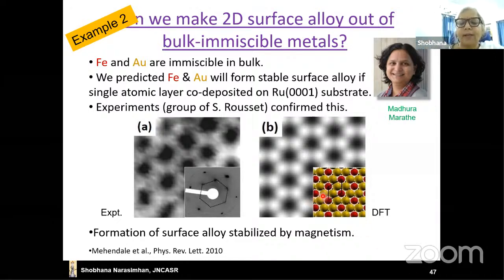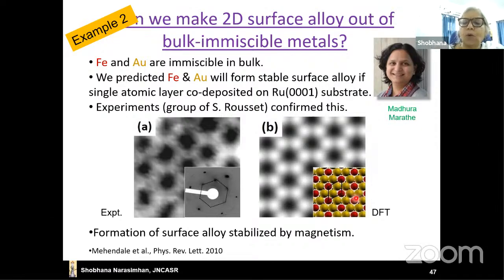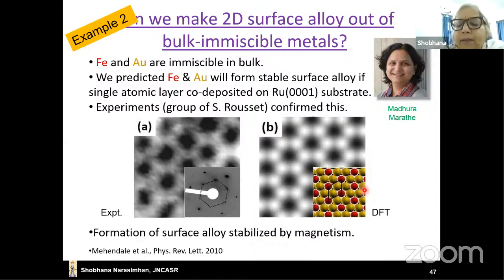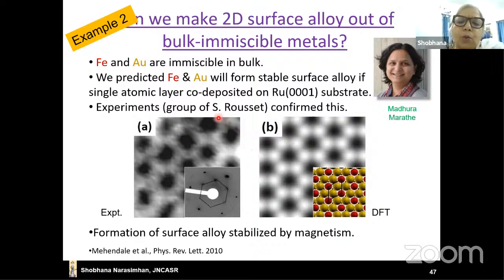In a 1:2 Fe:Au ratio on ruthenium, we predicted using DFT that this would be a stable alloy that would not phase-segregate. The red atoms are iron and the yellow atoms are gold. Our experimental collaborators in the group of Sylvie Rousset in Paris did the experiment. Their scanning tunneling microscope image shows the surface, where every dark spot is an iron atom and the light spots are gold atoms — indeed forming the predicted surface alloy.